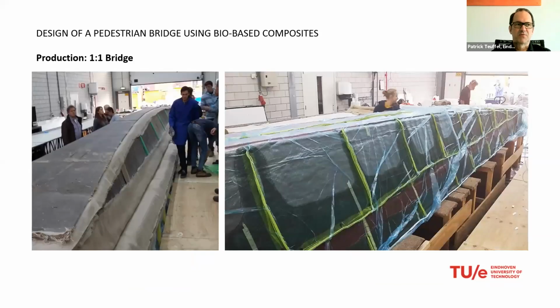Some more pictures from the production process. On the left picture, you can see the different layers of the material which were put on each other before we put everything into a foil, and then the resin was sucked into the mold by vacuum infusion. So you can see the yellow pipes. These are the pipes where the resin is sucked with a vacuum into the fiber material, and then after the hardening, of course, everything becomes a strong structure.